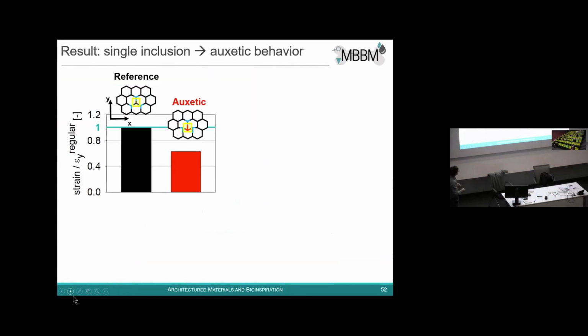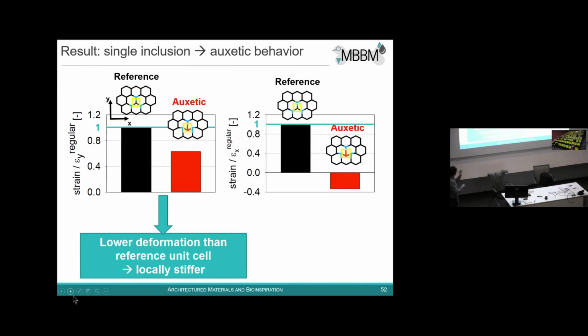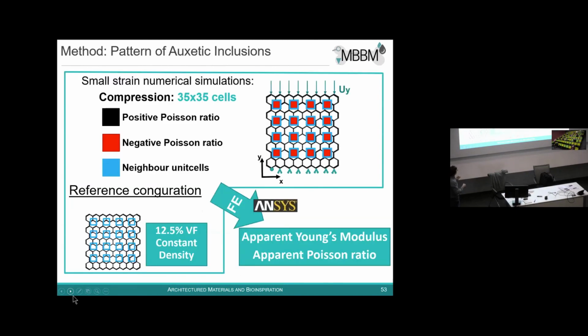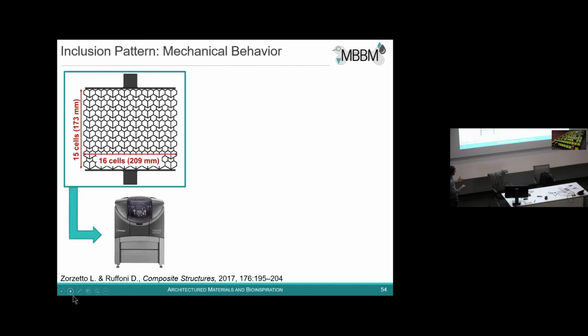And so we said, okay, since this is stiffer and has this auxetic behavior, let's now try to generate a pattern of inclusions where we introduce not just one as before, but several reentrant inclusions. We could introduce up to 12.5 volume fraction of reentrant inclusions, and we looked at what is happening in terms of apparent properties. Our assumption is that this lattice is stiffer because the inclusions have a contrasting deformation mode. The regular unit cells want to expand, the others want to contract, and this creates a contrast in the deformation mode, which then stiffens the lattice.